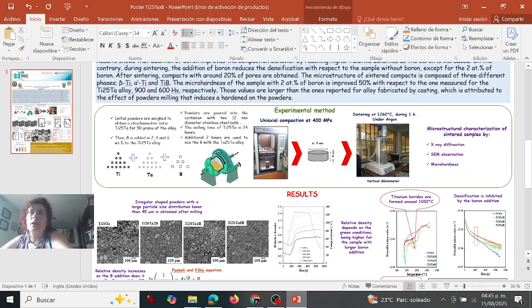Well, the initial powders were weighed to obtain a stoichiometric ratio of titanium 25 tantalum for 50 grams of the alloy. Then boron is added in 2, 4, and respectively 6% in the titanium 25 tantalum alloy. As a second step, we have the powders put into the container with 12 mm diameter stainless steel balls. The milling time of the titanium 25 tantalum was 24 hours, and the additional 2 hours were used to mix the boron with the titanium 25 tantalum alloy.